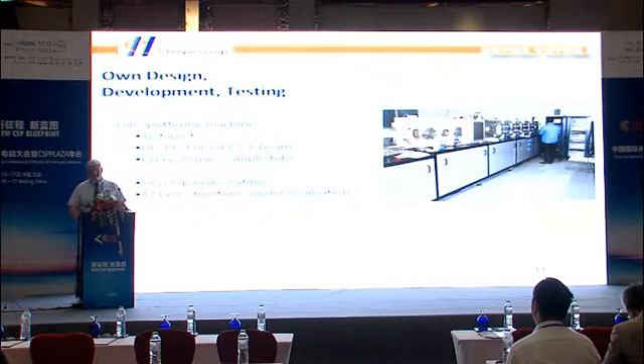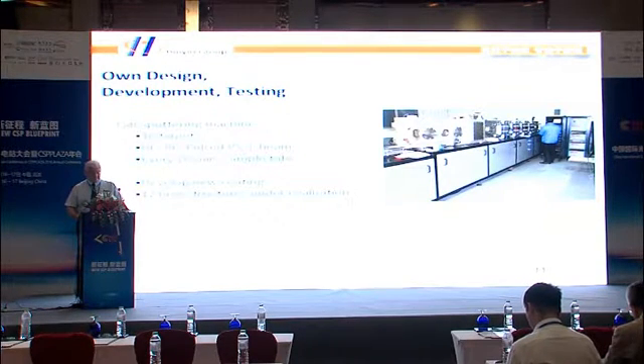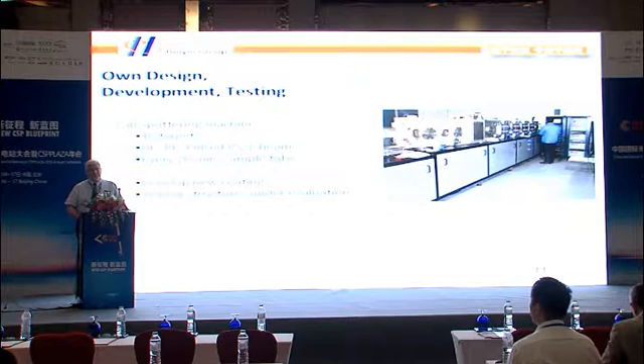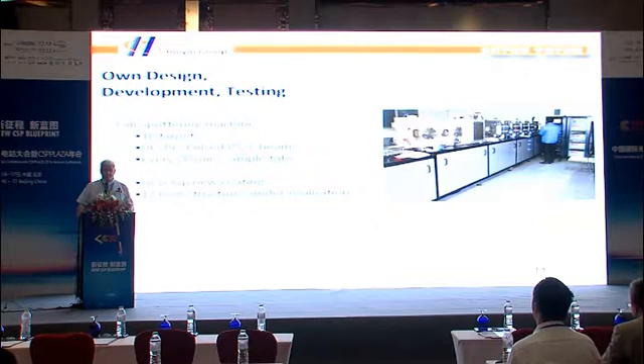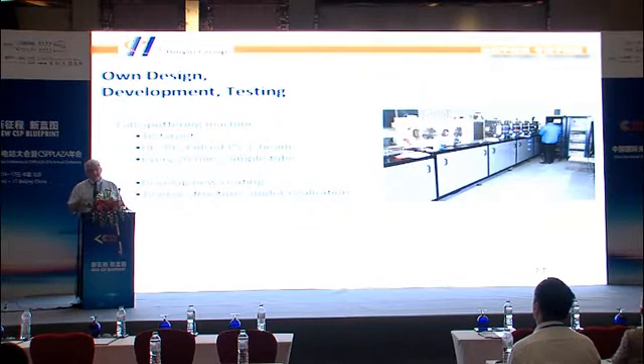We have our own development of sputter equipment, and here you see a sputter machine that was made for making lab samples. What became very clear to us is that we had to be able to test different types of selective surfaces in a very fast way. In this machine we can produce a sample about every 20 minutes, and this allows us to make thousands of samples. This machine has 16 targets, so we are able to deposit 16 different materials without breaking the vacuum. We have different power supplies: DC, RF, pulse power, and electron beam. So the whole range of deposition methods is available in that machine.